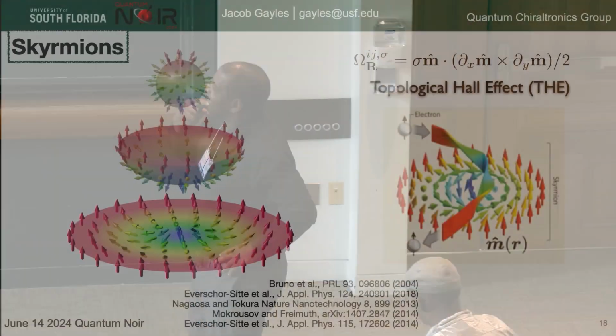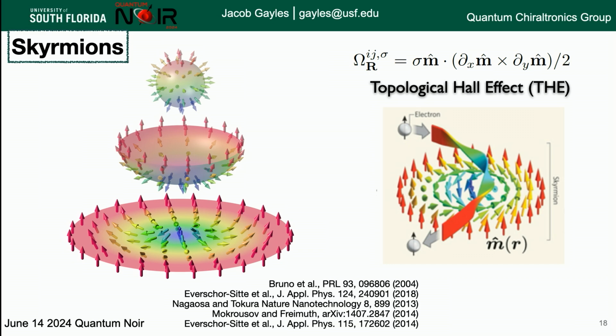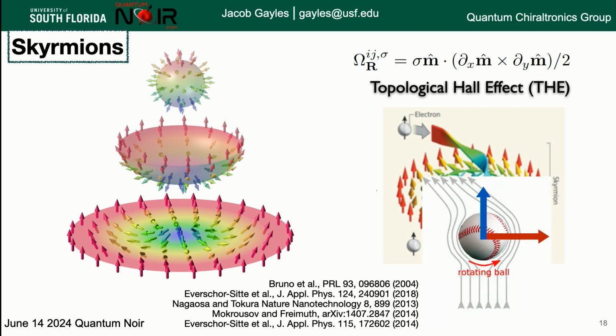So it's skyrmions. I kind of talked about this already, but you have a very nice response to currents. One aspect is you get a Hall effect, like I explained earlier, because there's a magnetic field. The electron sees an internal magnetic field, which acts differently on each spin, and so these spins will acquire again this Berry curvature. But now this is a real space Berry curvature, different than the Weyl semimetal. And because you want to conserve momentum, you also get an effect that you move the skyrmion when you reach critical currents.